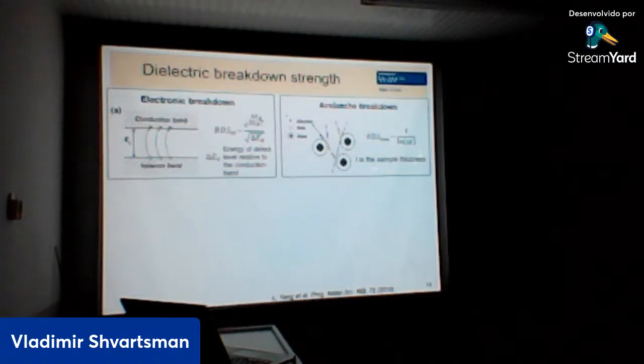So this breakdown strength depends on the energy of the defect level relative to the conduction band. In the case of the avalanche effect, this is a kind of intrinsic effect, but it more or less depends on the thickness of the sample. Of course, when we have a thick sample, the probability to have an avalanche will be high, since the electron will have more possibilities to interact with other atoms. Therefore, for example, the breakdown strength of ceramic samples is always smaller than the breakdown strength of films of the same composition.